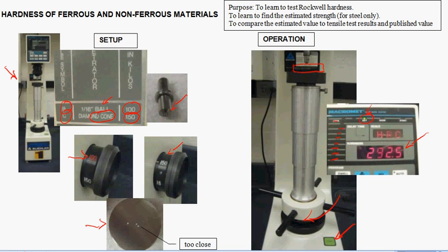When you put the sample on the anvil, you need to be careful. You can use the same sample for several tests, but the requirement is that you cannot perform a test too close to a previous test or too close to the edge of the material. So what you need to do is observe as you put the sample in place that your test is not closer than 3 diameters, 3 of these little penetration diameters, to another test, and then your test will be valid.